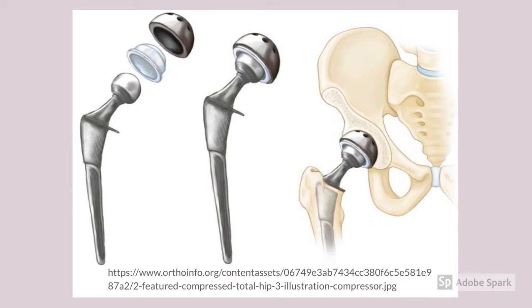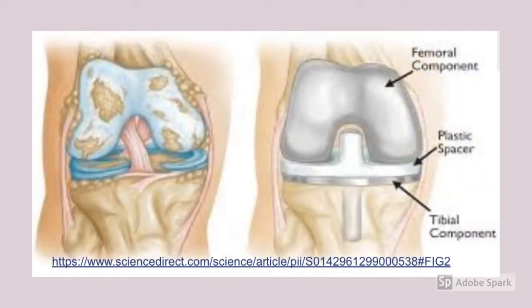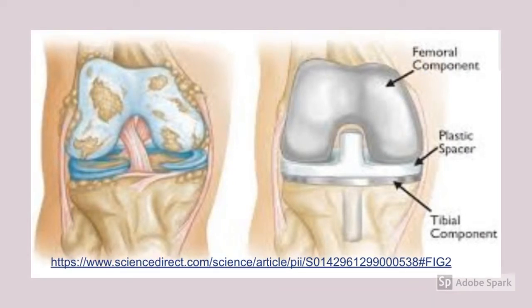Clinical and laboratory data has shown wear rates for cross-linked polyethylene are reduced by 10 to 50 percent. Due to the success of cross-linked polyethylene in hips, it was also introduced in knees.